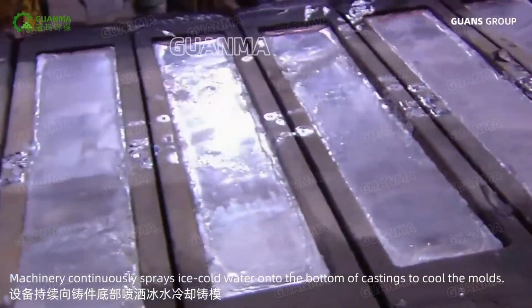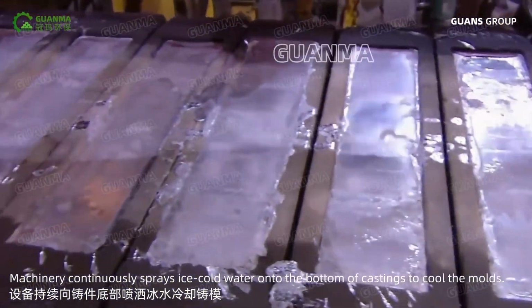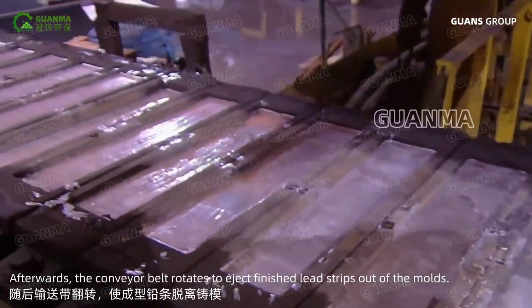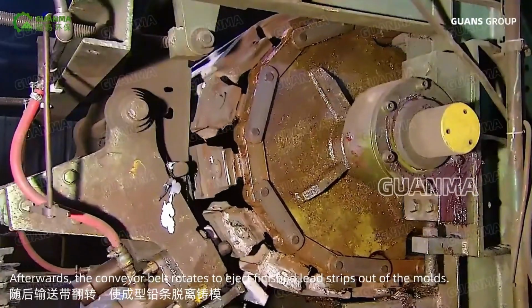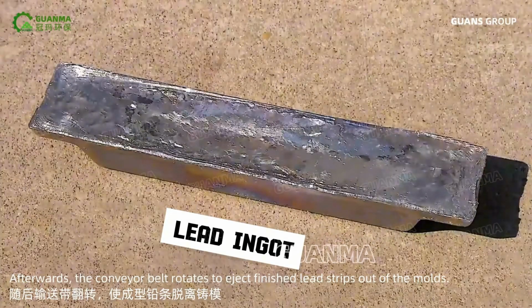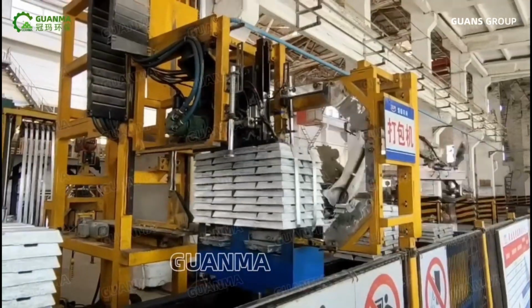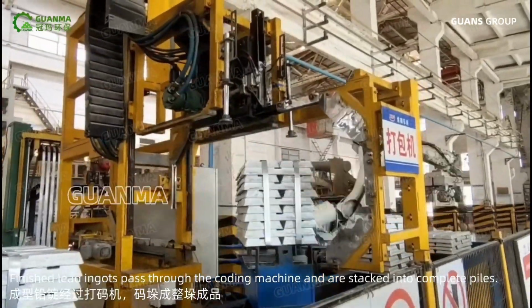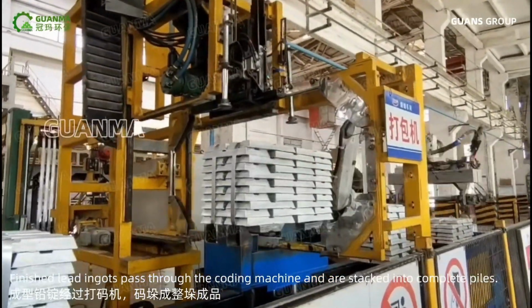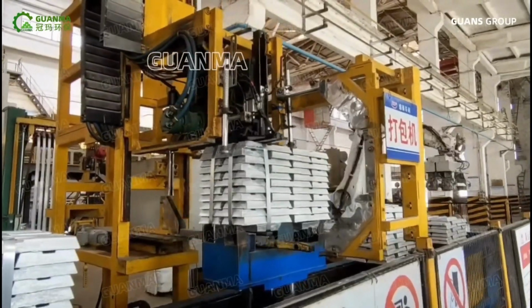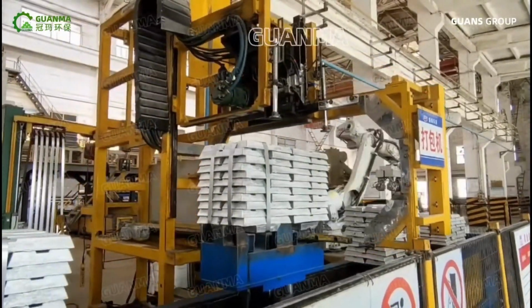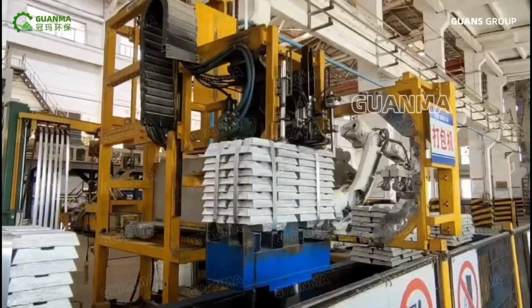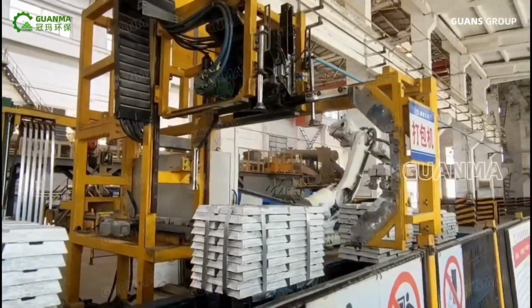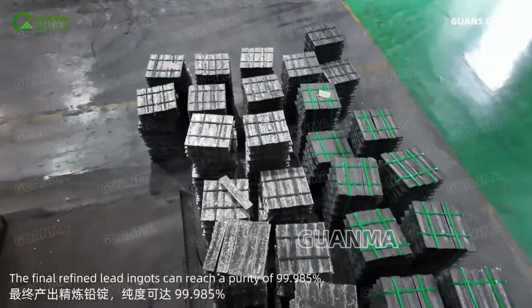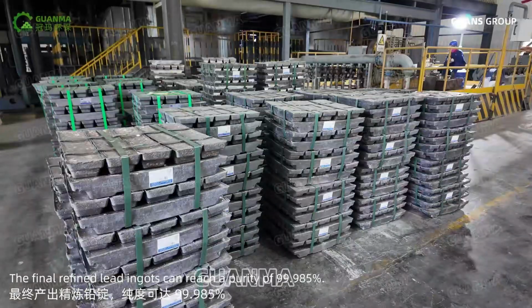Machinery continuously sprays ice-cold water onto the bottom of castings to cool the molds. Afterwards, the conveyor belt rotates to eject finished lead strips out of the molds. Finished lead ingots pass through the coating machine and are stacked into complete piles. The final refined lead ingots can reach a purity of 99.985%.